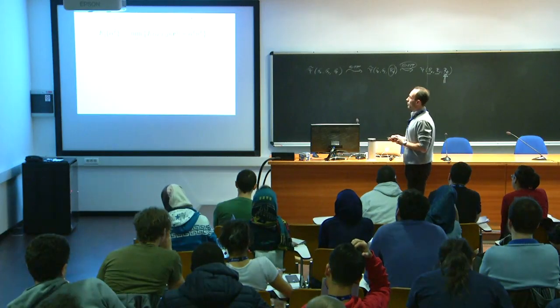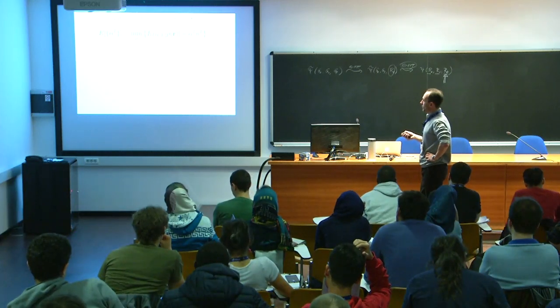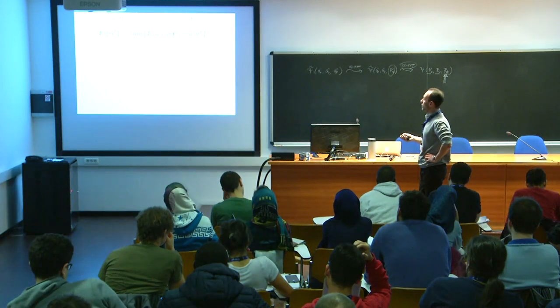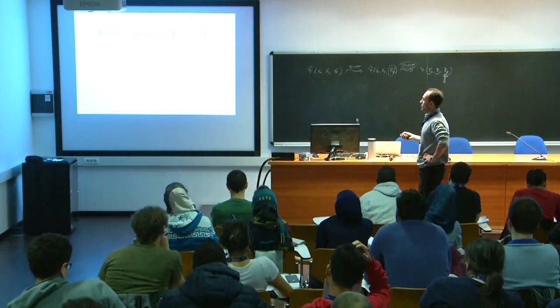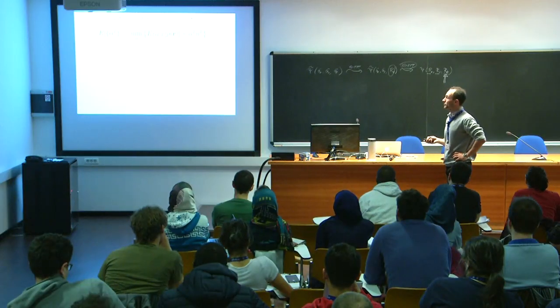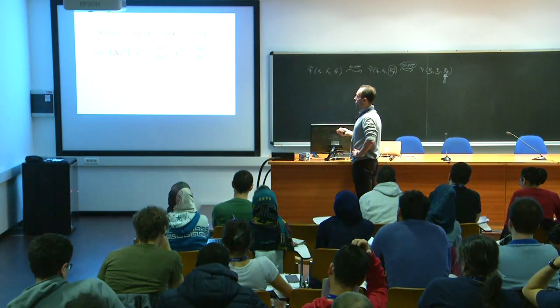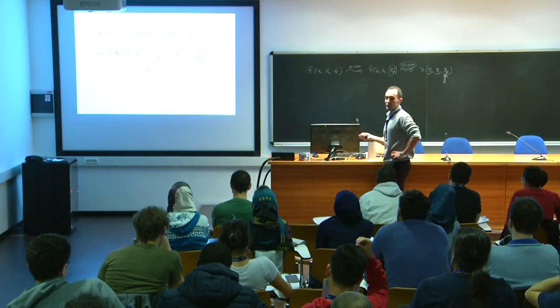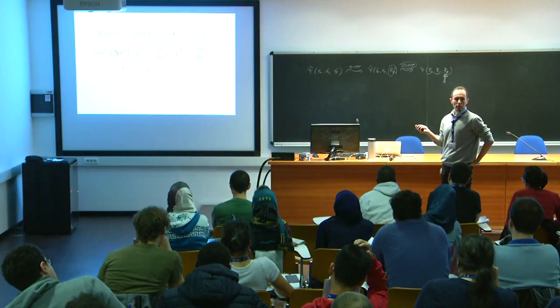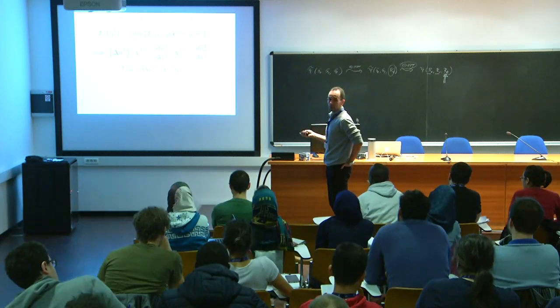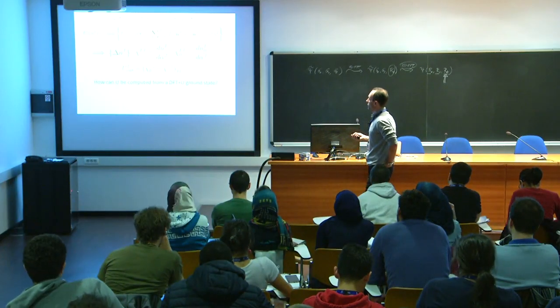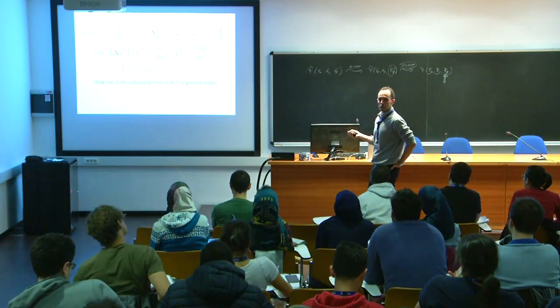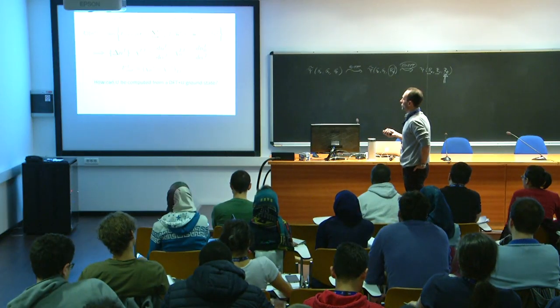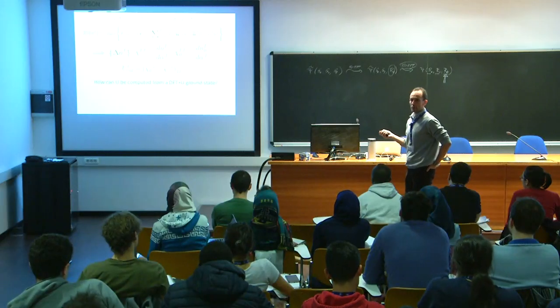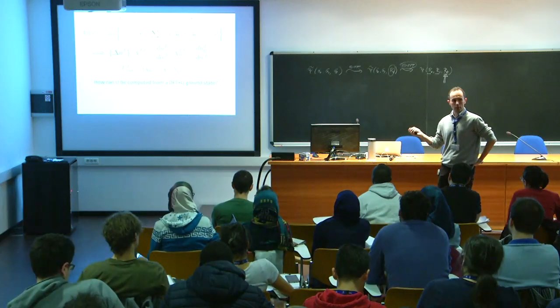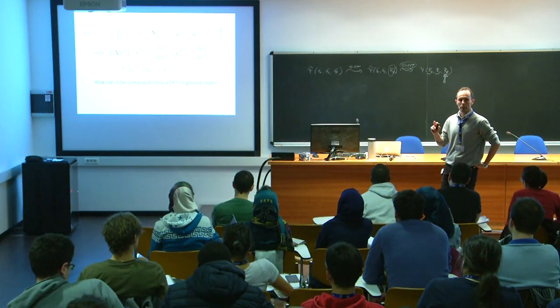This is not that difficult. I've shown you that we get these starting from solving the Kohn-Sham equation, which is equivalent to minimizing with respect to rho this functional where you have added this shift in the potential through a projector on atomic states. And then from there you get delta n, compute the response matrices the usual way, invert them, and then from the difference of the inverse you get the U, right? So extending all this machinery to work from a DFT+U ground state is not that difficult. You just need to add an extra piece in the functional, right? Well, it takes a little detail. You should keep these occupations fixed, because otherwise you get this piece also contributing to the second derivative, while instead the U is the effective second derivative of only this piece. That's the only little detail that you get.